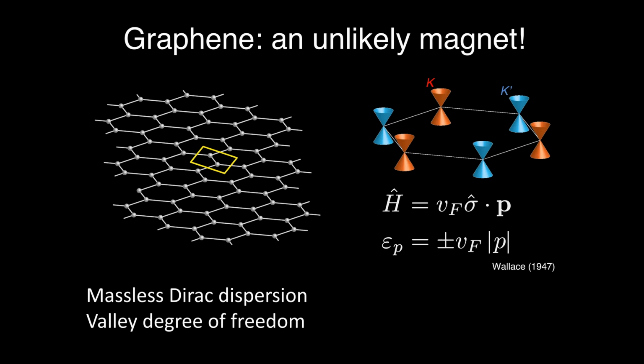because if you think about monolayer graphene and its electronic structure, it's a very unlikely magnet. So monolayer graphene, it's just a single layer of carbon atoms. It's the elementary building block of all of the graphene, all of the graphite type materials that you're going to study. And its electronic structure famously is described by these massless Dirac electrons, where you have 2 flavors per spin, so 4 flavors total. One of each of these 2 flavors is located at the corners of the Brillouin zone. Okay, and if you think about, is this a likely candidate to be a magnet? The answer is not really, because this massless Dirac dispersion basically means the usual ingredients of magnetism are not there, and the fact that it's made of carbon doesn't help either.